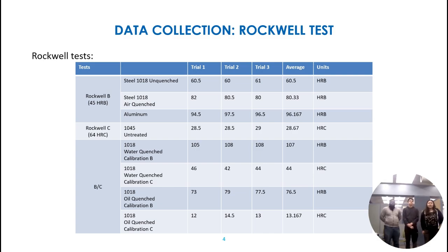The Rockwell tests were done using a Rockwell hardness testing machine. The B test is done with the steel ball with the 980 Newton load for softer materials. The Rockwell C test is done with a diamond tip and a 1471 Newton load for strong materials. We did both tests for water and oil quenched steel and compared the hardness.